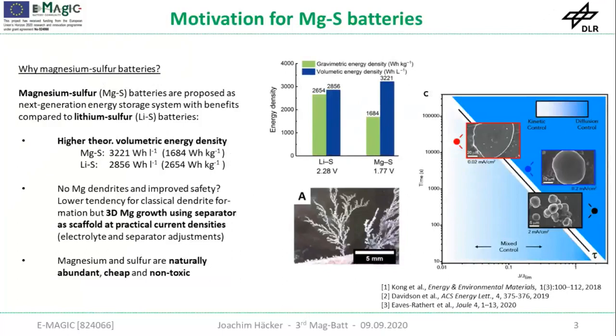Normally on this introduction slide, you can read that magnesium dendrites are not present in this system, but I think this is not the case. There is a lot of literature showing that classical dendrite formation is not present due to a higher surface diffusion. But indeed, 3D magnesium growth using the separator as a scaffold at practical current density is still observed. You can see on the right side a recent publication at practical current densities. There's this spherical growth, which might be tuned by electrolyte and separator adjustments, so this issue might be overcome in the future.